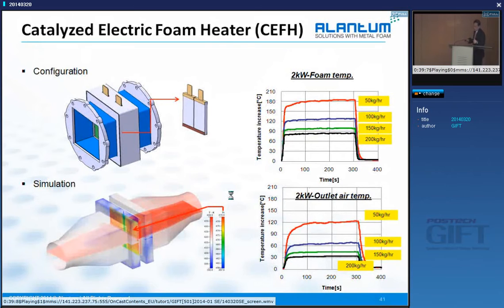This is another breakthrough, a real innovation, if we are successful in this business. As you see, our metal foam is an electrically conductive material, right? Ceramic is not. So we can flow electricity through it, and then it works almost like a heating unit. Basically, once soot or other contaminants are collected on the filter, the way to remove them is called regeneration. We regenerate by burning them off, raising the temperature to about 400 or 500 degrees, then it refreshes. Once our foam is electrically conductive, we can raise the temperature that much, and then we don't need any active regeneration system. But it's still under development.